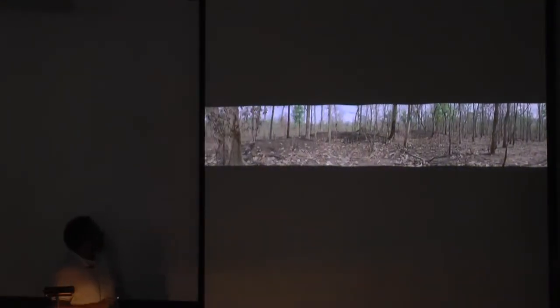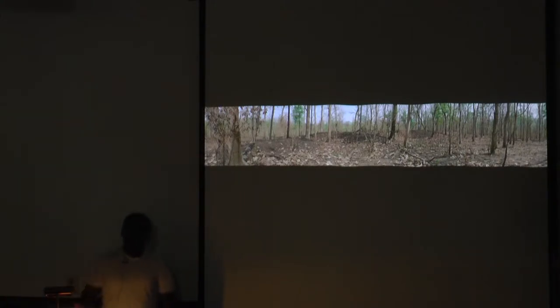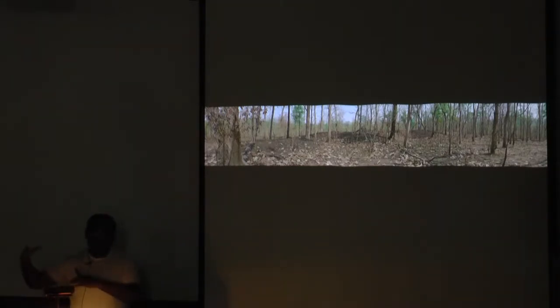In the forests, we find huge areas with a series of slag heaps. So here you can see this is one slag heap, this is another one, this is another one, and there are a lot of slag heaps further down. So these were probably a series of smelting episodes. I'll explain later as we go along, and they probably indicate specific time periods. Each slag heap was probably from a series of 5-10 years of intensive smelting, and then the community moved away and came back later.